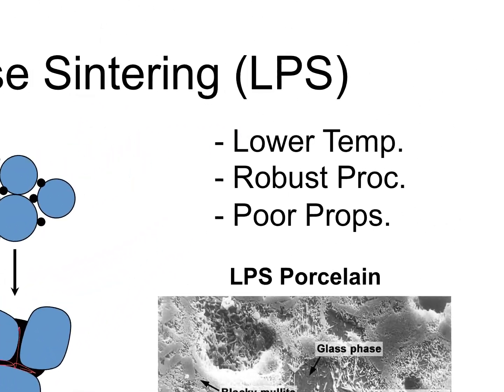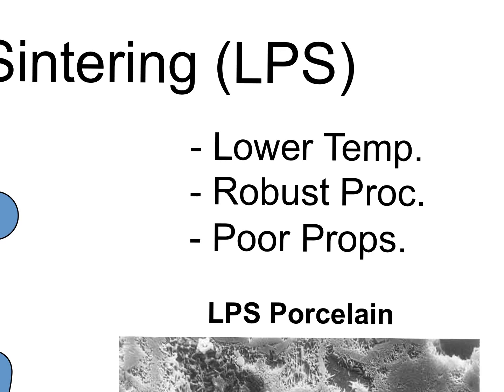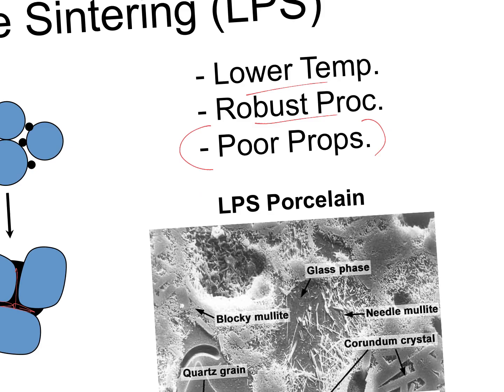You get this process of densification at lower temperatures because you're not relying on vapor phase transport anymore. Now you have liquid phase transport, which is way more efficient, and you have liquid phase, which doesn't go away. All right, so you have plenty of diffusion going on inside that liquid. So we don't have to worry about pathways to the surface because the liquid forms a permanent pathway to the surface. And so you can have lower temperatures, robust processes, but of course the downside could be poor properties. It depends on what it is you consider poor properties.